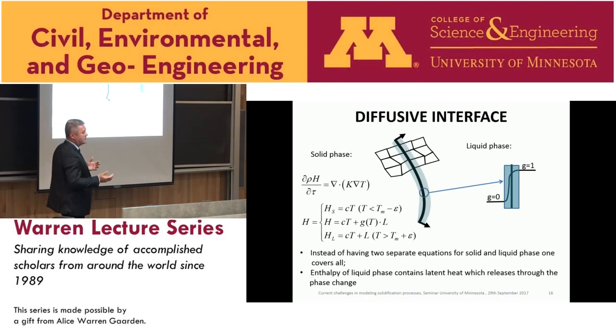We assume that C is equal between liquid and solid, but it's not. But we wanted to first start from very simple models just to understand phenomena and then introduce more complex details later. H_L is C times T plus L, where L is the latent heat. And in this diffusive zone, H is a combination of solid and liquid. If you combine those two, H_S and H_L, you will get this simple equation, C times T plus G, which is a function of T, times L.